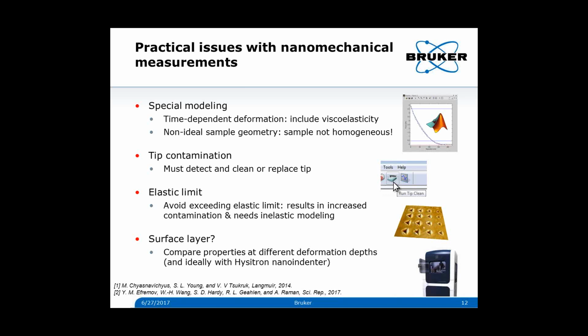Elastic limit essentially is another issue. If you put too much force on, you will end up making holes in your sample, and that really results in increased contamination, and it also requires different modeling. And then finally, a lot of times, if you have numbers from DMA or something like that, those numbers are for a bulk material. So there could be a surface layer on your sample that you're measuring with your AFM.